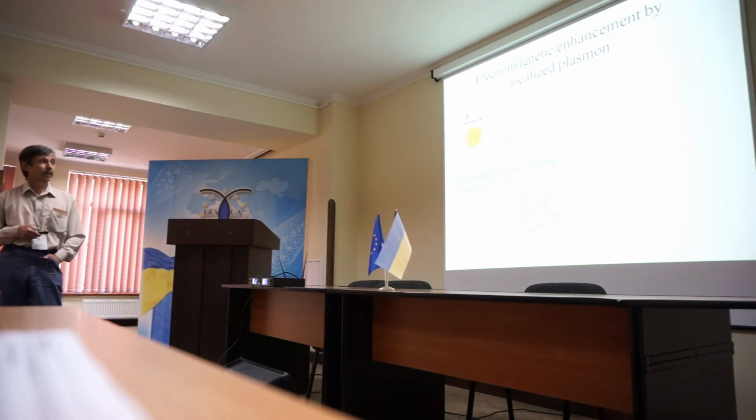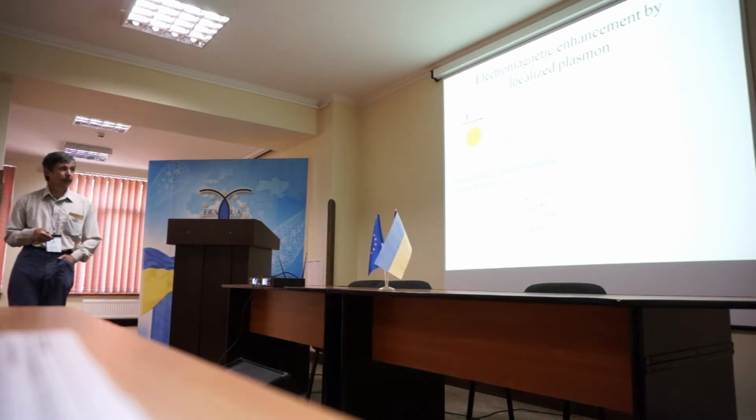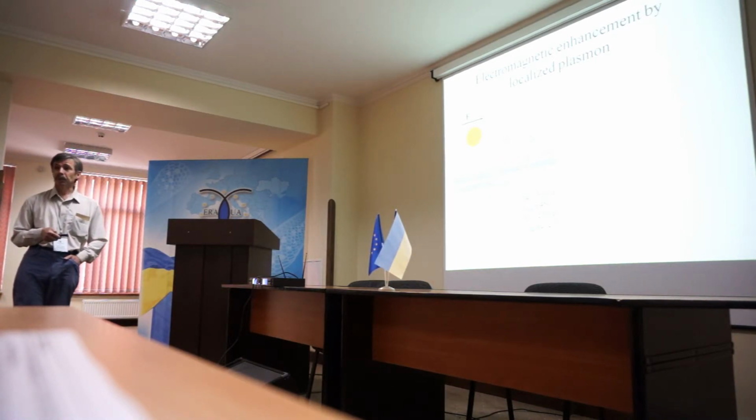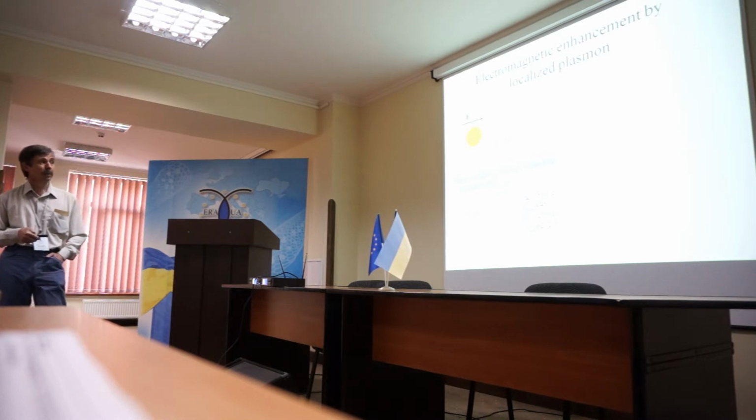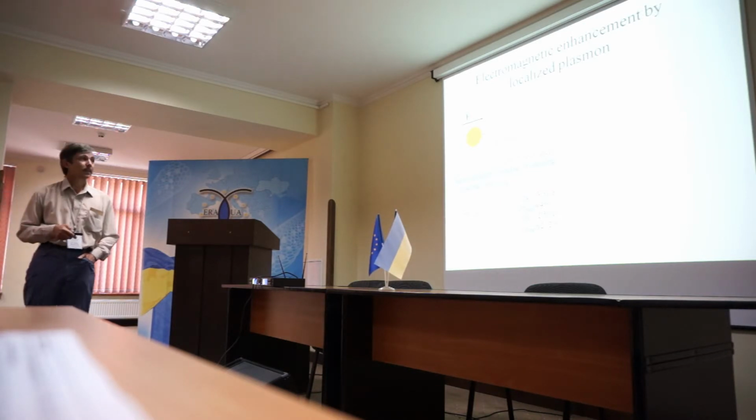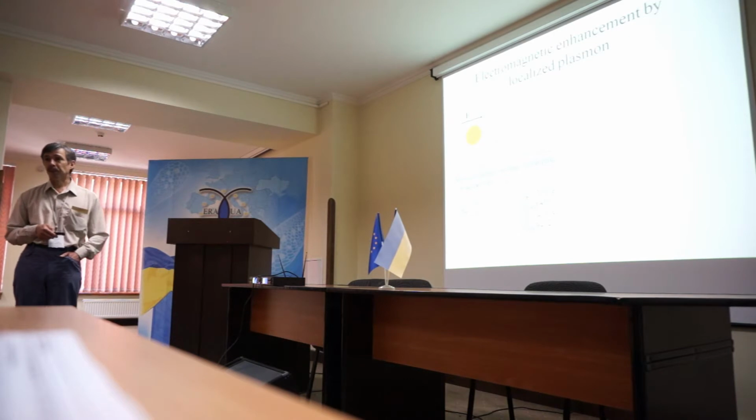So if we approach this condition, we have excitation of the resonance, but we have no divergence in this case, and we can define that the highest enhancement of the intensity on the surface of this particle is described by this expression. It is restricted by the damping, so the imaginary part of the dielectric function of our material. And you may see that the biggest enhancement we can expect for silver, where the damping is low, it's something like a few hundreds. But for gold, it's only 2 and a half. It's just because of the higher damping of gold.